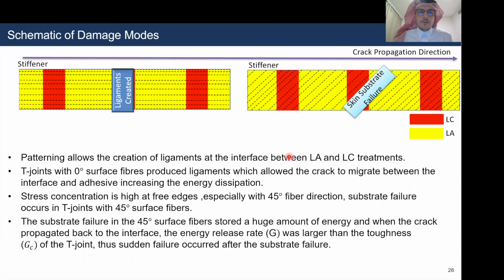So in the first case scenario, which was the 0-degree fibers, the phenomenon of adhesive ligaments was created due to the patterning at the interface between LA and LC treatment. These ligaments allowed the crack to migrate between the interface and the adhesive, increasing the energy dissipation. However, a different phenomenon occurred with the 45 degrees, which is known as a coupling edge effect. As we know, the stress concentrations are very high at the free edges in general.